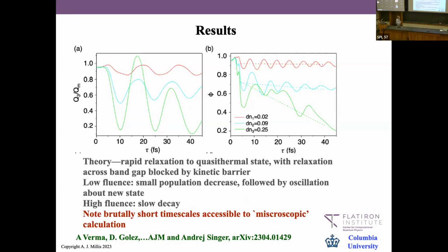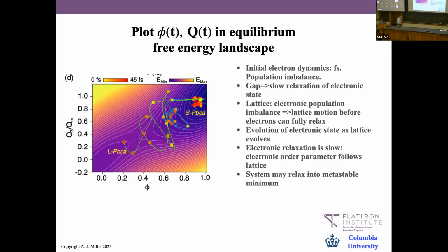So here what I've done is put these calculations on top of my free energy landscape. What you see is that the initial pulse, if it's weak, just causes the system to bounce around this minimum - that's what we expected from our previous calculation. If it's stronger, it shifts you in the electronic coordinate, but not in the lattice coordinate, out to somewhere here. And if it takes you far enough out, then you can start to fall down this way and eventually wind up in this minimum.